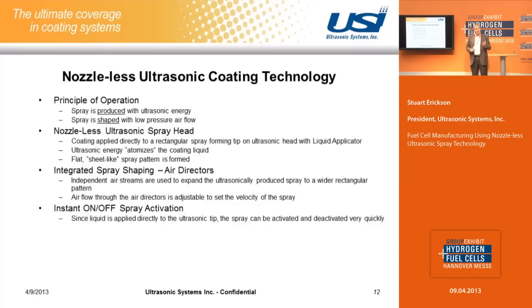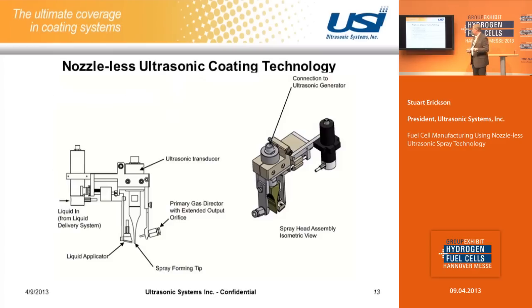Another attribute of this technology, since we don't have a nozzle or anything that the liquid has to go through, is that we can turn the spray on and off instantaneously. And that is important in a production environment. So the ultrasonic head has an ultrasonic transducer, and there's no liquid passing through the ultrasonic device. We have the vibrating tip of the head, and we apply the liquid directly to that tip, and then we use low pressure air to shape the spray. So there's no type of a nozzle. The tip of the head has a rectangular shape, and the spray it produces is a rectangular shape.